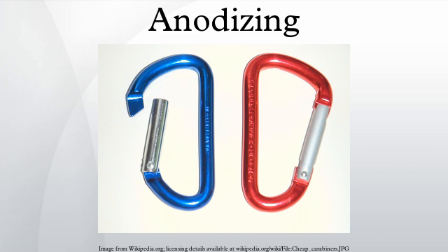Chromic acid produces thinner, 0.5 μm to 18 μm more opaque films that are softer, ductile, and to a degree self-healing. They are harder to dye and may be applied as a pre-treatment before painting. The method of film formation is different from using sulfuric acid in that the voltage is ramped up through the process cycle. Sulfuric acid anodizing. Sulfuric acid is the most widely used solution to produce anodized coating.